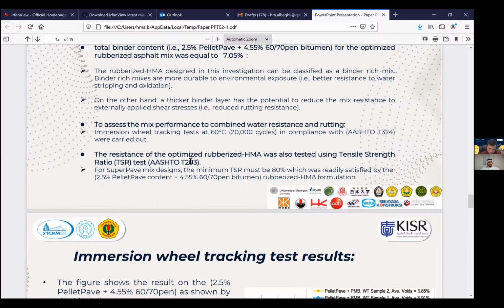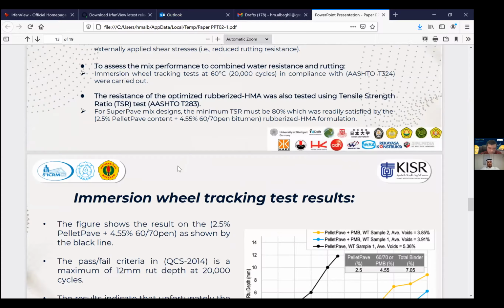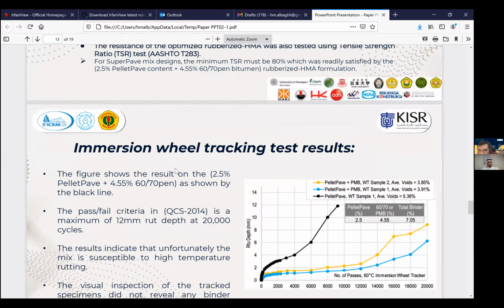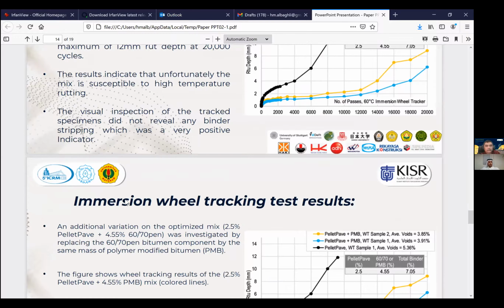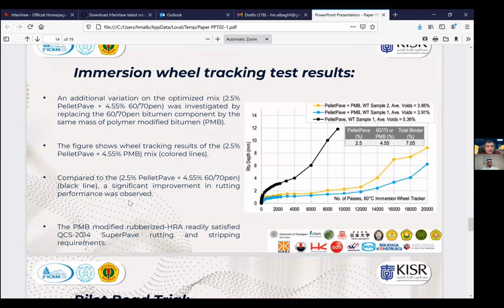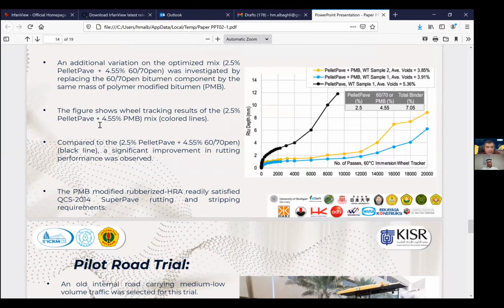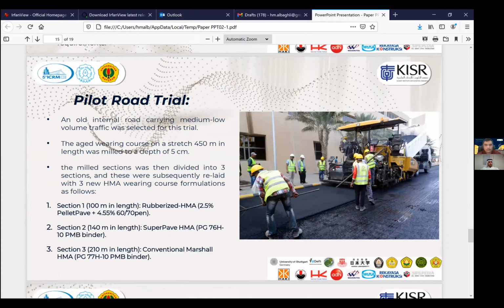The new mix satisfied the newly adopted Superpave requirements for both rutting and stripping, as well as for tensile strength. Then we moved to make the pilot road. We wanted to try this mix practically in the field, and in order to do that, we wanted to assess the performance of the optimized Pellet Pave rubberized asphalt during full-scale production, transportation, paving, and compaction operations.